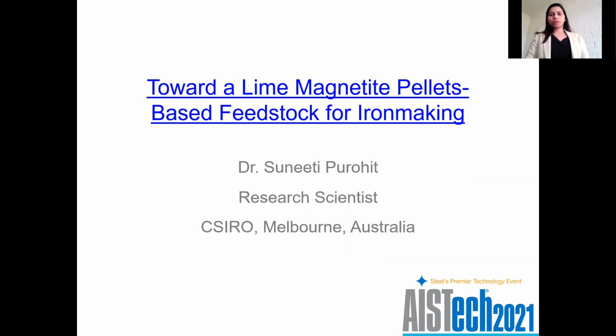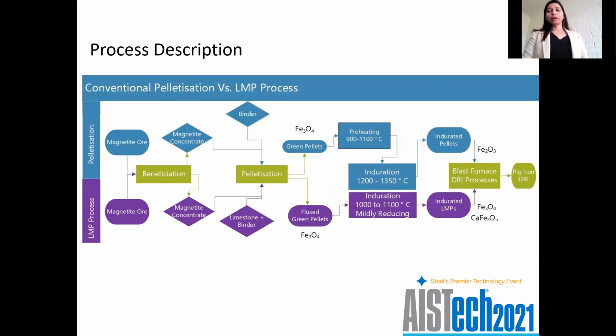So I'll be talking about an alternative iron agglomeration process that we call the lime magnetite pellet process, or LMP process. When we look at the current way of magnetite ore agglomeration, we start with magnetite ore, beneficiate it to concentrate, then the concentrate goes to a balling stage, and the green pellets are then charged to a two-stage heating process. One is preheating at 900 to 1100, followed by induration at 1200 to 1350 degrees centigrade. And then the indurated pellets are charged to the blast furnace or DRI processes for iron making.